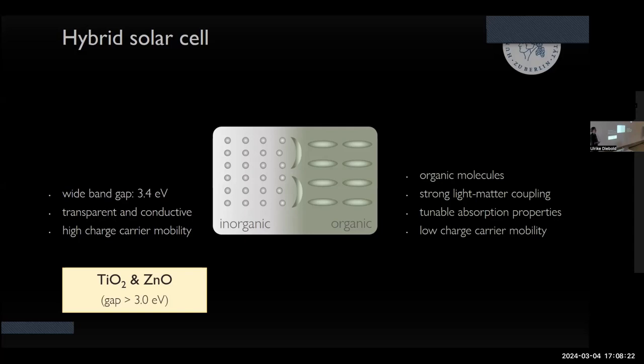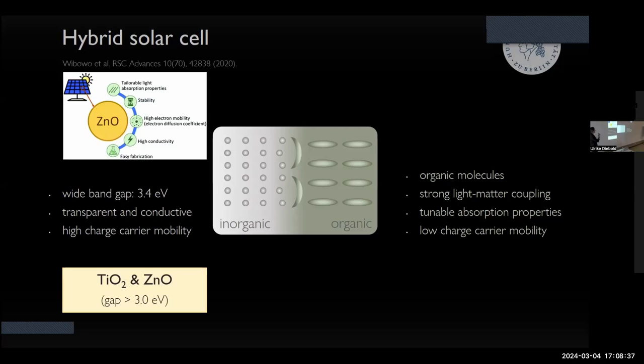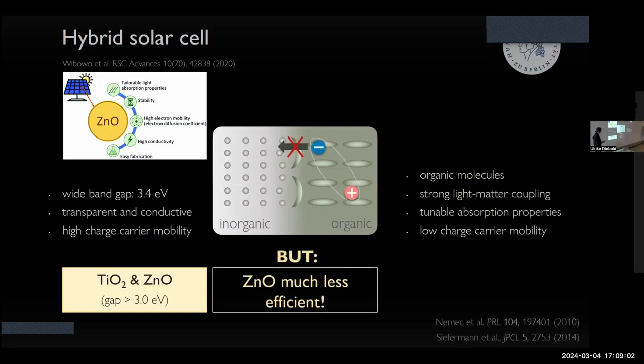and they have quite similar properties except for the dielectric constant. The dielectric constant of TiO2 is much larger than zinc oxide, and of course they have a different structure. Zinc oxide is a promising material for such applications, also for LED applications, and it's even better suited because you can fabricate nanostructures much more easily than in the case of TiO2. But unfortunately, it doesn't work very well in reality. For some reason, at these inorganic-organic interfaces, the charges are not efficiently separated if you use zinc oxide. And this is one question that we wanted to answer, and the reason for this.